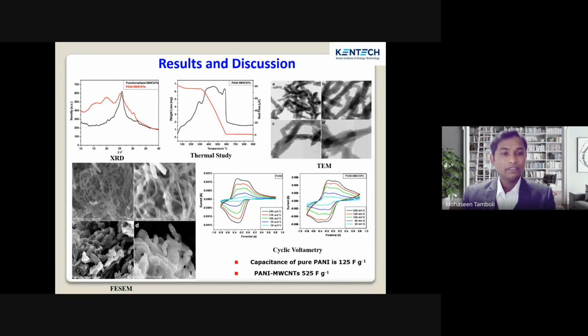In the thermal study, you can see polyaniline MWCNT shows a three-step decomposition process, showing that it is a good, stable conducting polymer. And we have also checked this material for morphological aspects. In the case of morphology, we can observe the 20 to 25 nanometer carbon nanotubes, and when we coat the carbon nanotube, the size is increased due to the coating of polyaniline on the carbon nanotube.